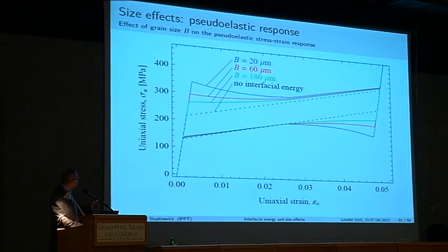Okay, so this is the effect of this specific grain size on the macroscopic response, and what we see is that the smaller the grain, the larger the hysteresis, and also the transformation strain for initiation increases. So this is a kind of similar effect to the Hall-Petch effect. Smaller is stronger in this range of grain sizes, at least. Not much more to say about that.